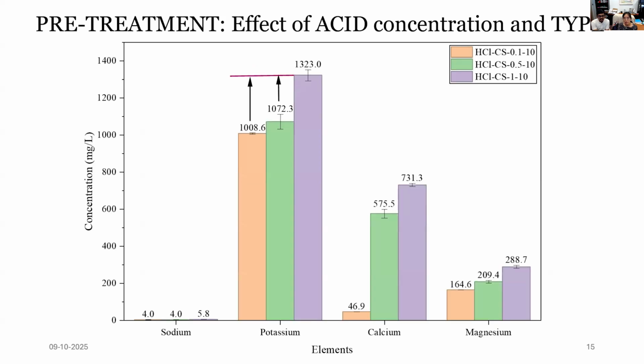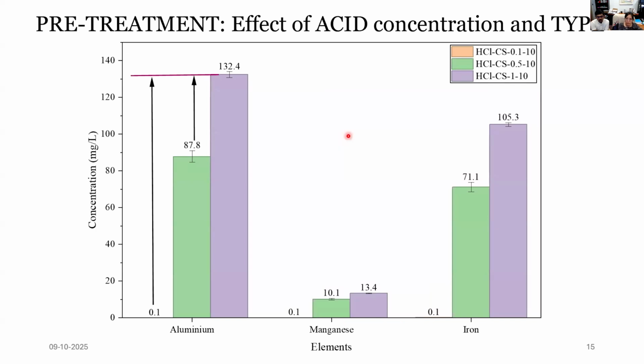So we could understand from here that when we used hydrochloric acid to pre-wash the material, and analyzed the leachate, increasing the concentration of the hydrochloric acid enhanced the amount of impurities released from the system. And if we look at heavy metal release such as aluminum and iron, it becomes very selective, because for a lower concentration of 0.1 normality, the amount of heavy metal released is very minimal. However, when we increase the concentration to 0.5 normality, there is a significant release of aluminum, iron, and manganese from the corn stover ash.